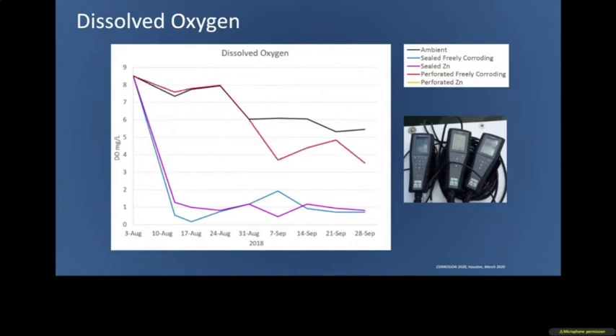If we look at the perforated freely corroding steel pipe, it basically follows the ambient oxygen concentrations, but both the perforated freely corroding pipe and the cathodic protected pipe, after about a month, started to show a slight decrease in oxygen. And we assume that was due to the fact that we started to get marine life actually living within the pipe, and their respiration will basically reduce the oxygen concentration.